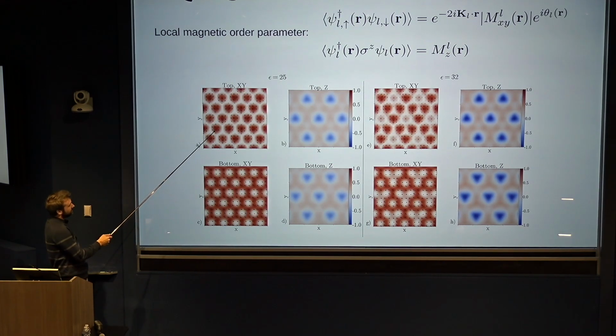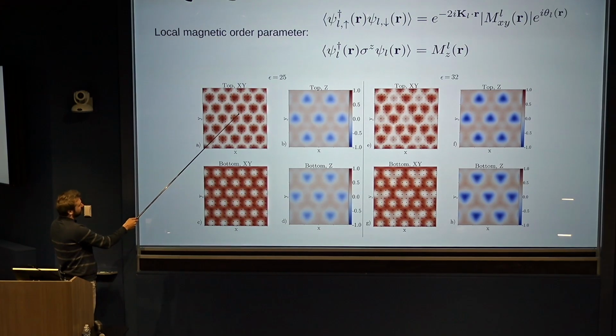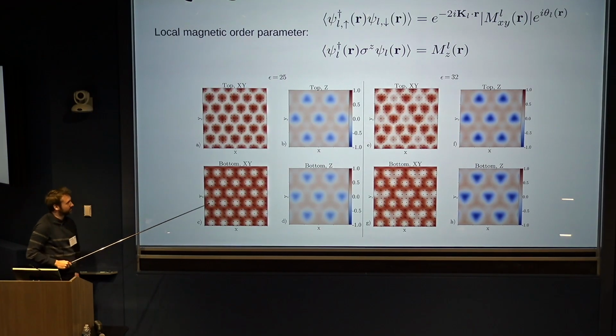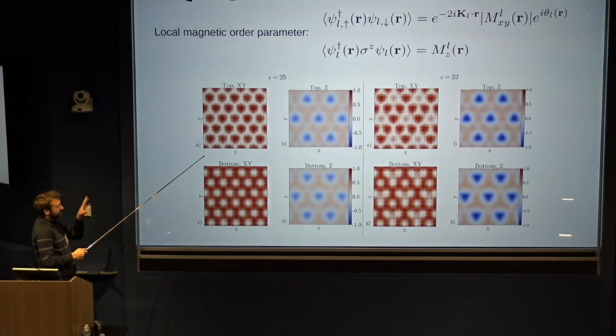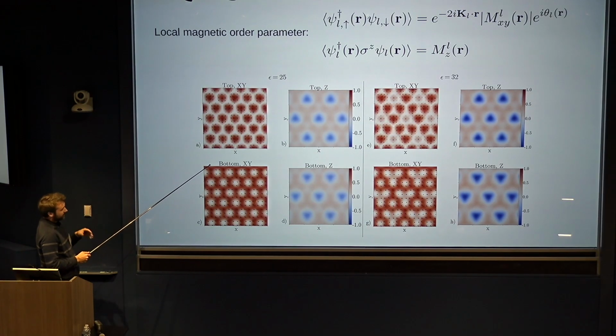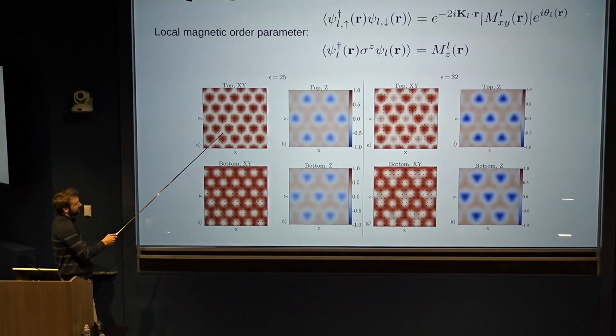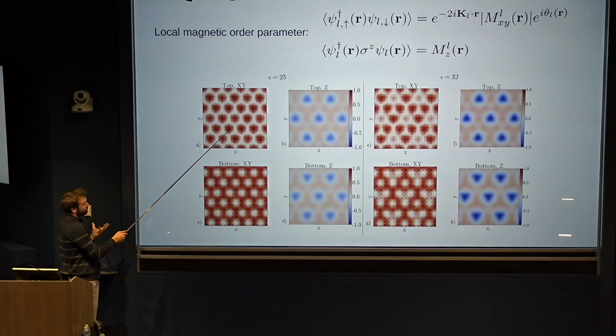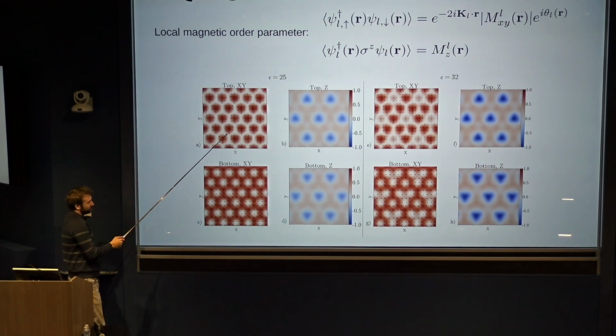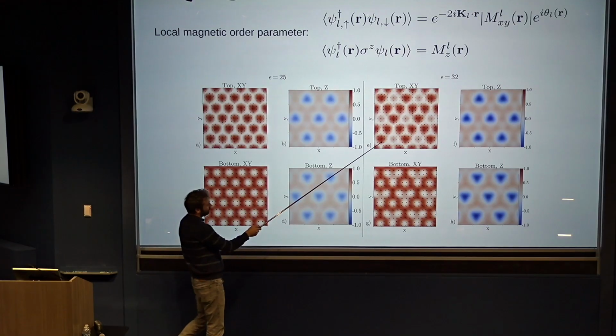If you look at the top layer, you clearly see this triangular lattice, and that's the Moiré superlattice. You also see that this in-plane magnetic moment makes this familiar 120-degree antiferromagnetic state on this triangular lattice. This state is not the unconventional state that I have been referring to. It had already been found before in other theoretical studies in this system. But the state we find actually is this one.